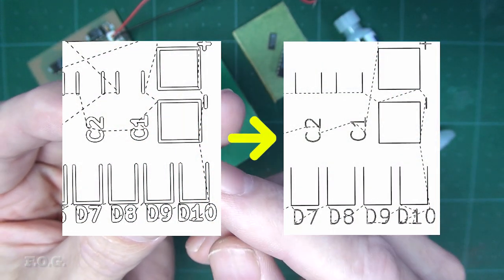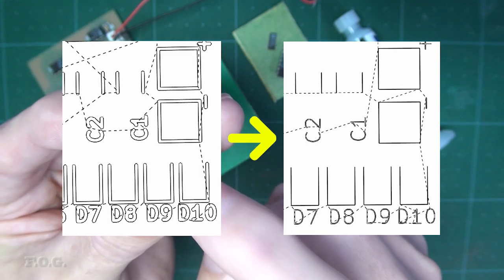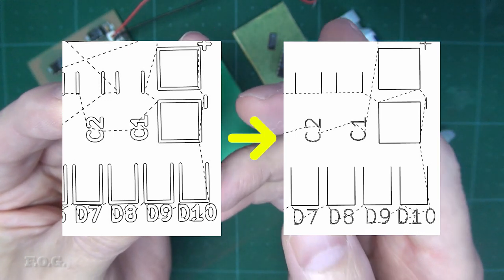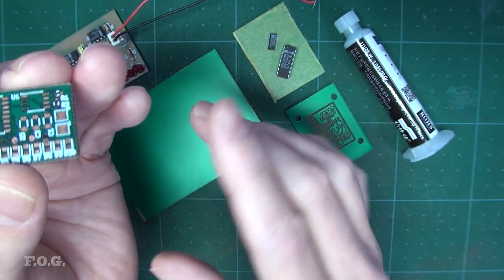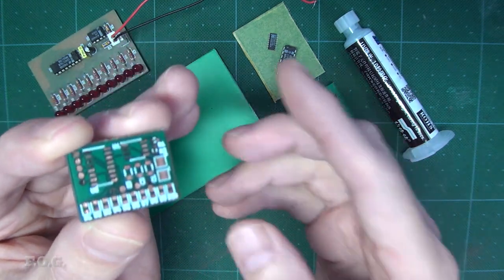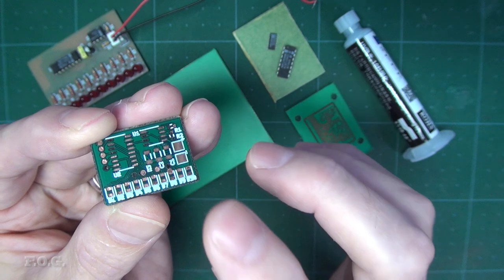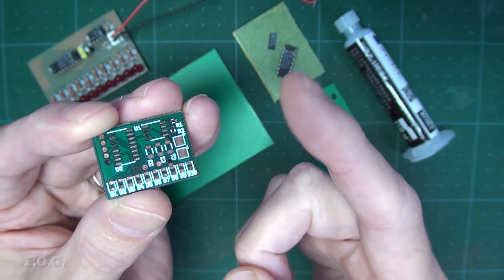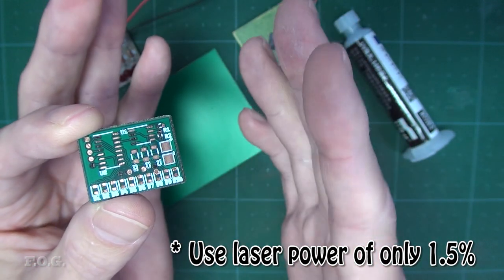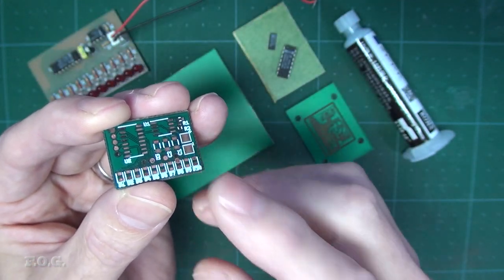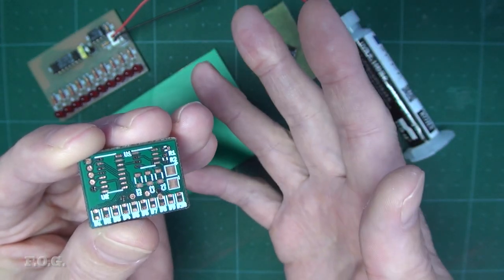I think for the next try I will change this setup so the laser burns on the inside area of this text and not on the outline like you see here. I think that should give a better result. And as this new resin coat is clearly thinner, I will also drop the laser power from 50% down to 25%. And finally, after embedding the resin I'm going to use the same G-code path one more time and run the laser over it using a reduced power of around about 1.5%. I'm thinking that this will make the text cure just enough so that it allows me to clean off the surface of the board without disturbing the white text.